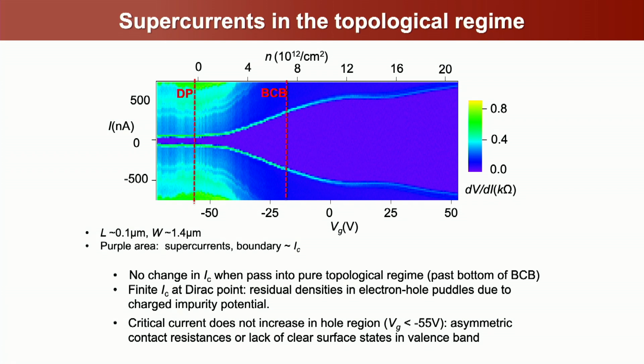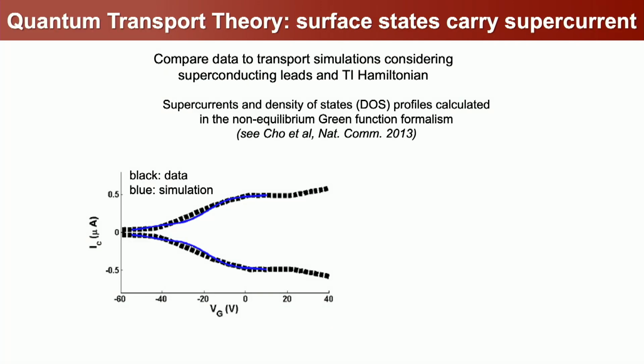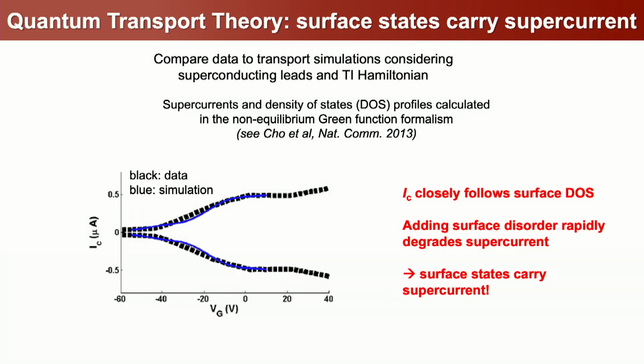But it turns out that that's okay, because when we compare this to simulations, what we see is that basically the surface states are carrying all the supercurrent, even when you have bulk states available. And so this is one of the things that makes coupling topological insulators to superconductors really interesting: even if your Fermi level isn't at the Dirac point and you couple it to a superconductor, your supercurrent still mainly flows through the surface states.